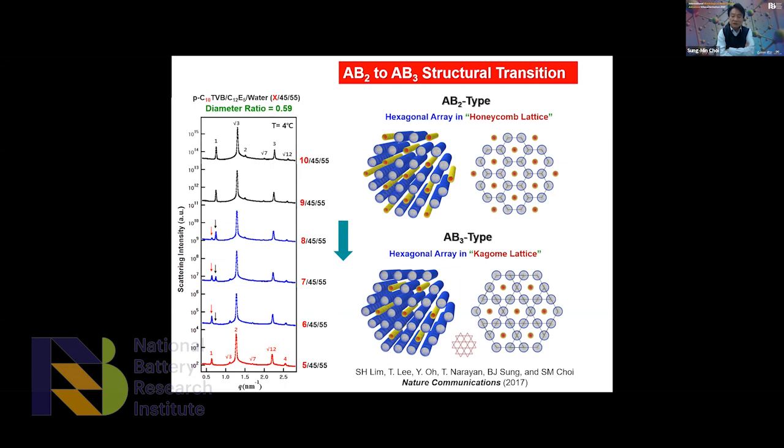So this is actually mixing one-dimensional nanoparticles of two different diameters. Usually these don't form superstructures. They usually phase separate. But by using this surfactant system, a model system with the nanotube, we show that in fact for this 1D object, by properly controlling it, we can have binary superlattices with different symmetry.